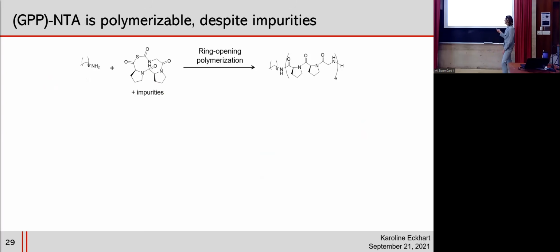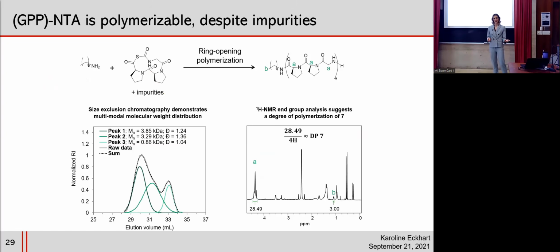So we treated the GPP-NTA with a primary amine and polymerized it, and then analyzed the product by size exclusion chromatography and NMR. And we can see here that the SEC has a multimodal peak distribution, which suggests multiple polymer species present in the sample. Typically in a controlled polymerization, you just have one peak in the SEC and it's very narrow. So we can see here that we clearly do not have control over this polymerization, and it's probably because of the presence of those impurities. We also analyzed the polymer by NMR, and we determined that the average degree of polymerization was about 7, which really means 21 amino acid units in a row, because each monomer is 3 amino acids.